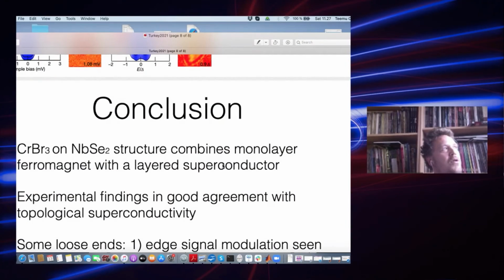In some sense, this is a much more complicated system than our theoretical model is taking into account. Of course, at higher energies, there is this charge density wave stuff that could somehow affect things, and then there is the contact between the magnetic layer, the chromium tribromide monolayer, and the surface of the niobium diselenide. It's very difficult to quantitatively get the correct spectrum, and our theoretical model is a caricature which just takes into account the most dominant things. I would also say that it is a logical first try. So there is definitely a lot of room to improve the theoretical modeling.